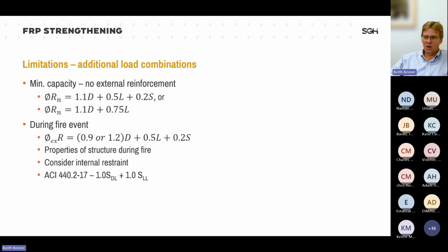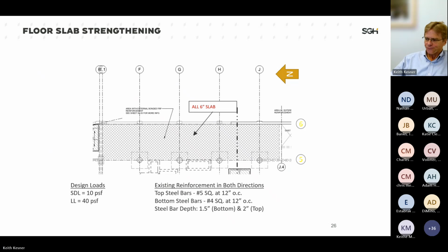The other consideration is that during a fire event, you need to have a minimum strength of the structure, and that's similar. But when we're doing this, we're considering the properties of the concrete structure during the fire event, as well as the internal restraint provided by the structure. So there are some limitations in terms of load combinations when we are using FRP. Now I'm going to go through a case study, not a super detailed one. We have an existing two-way slab, a 6-inch slab. You can see some drop panels that are present. Those are 2-inch thick drop panels. And there's an interest in having a superimposed dead load of 10 PSF and a live load of 40 PSF.